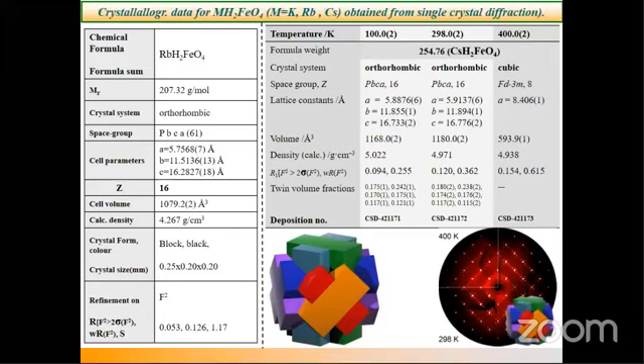At a certain phase transition, what is happening is that we have one orthorhombic phase that is transformed into a cubic phase. How can one see that? Just by single crystal X-ray diffraction. You can see these are the single crystal diffraction spots. At 400 K, these are very well refined, a high symmetry structure, which is showing the different diffraction planes. At 298 K, there are certain systematic absences and satellite reflections, which hints that the phase at low temperature is different from the high temperature. So there is a phase transformation taking place.